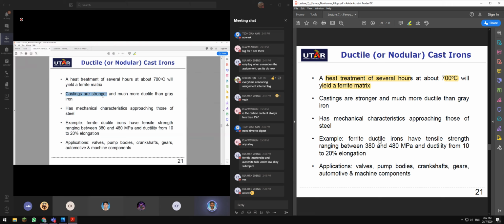These castings are stronger and much more ductile than grey iron. Very high strength, and more ductile than grey cast iron. And ductile cast iron retains the ductility while having high strength as well. Therefore, it has mechanical characteristics approaching those of steel. For example, ferritic ductile irons have a tensile strength ranging between 380 to 480 megapascals and a ductility of 10 to 20% elongation.